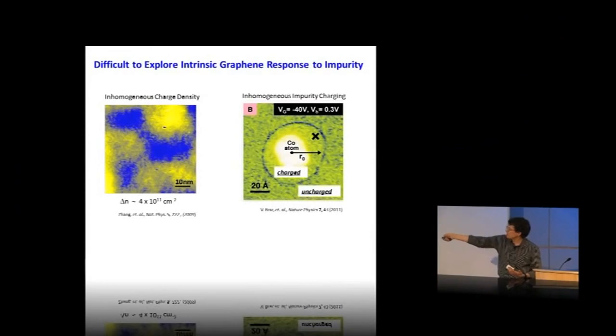Nothing is ever perfect, and one of the problems that we have, because we've been trying to do this, is that the graphene is so inhomogeneous. This is an STM image of the electron-hole puddles in graphene that you've already heard about. And this electronic inhomogeneity in graphene makes these kinds of measurements hard for us because it obscures what's happening. Because if I put one atom down, say I put an atom right there, then if there's some charge distribution around that atom due to the Coulomb impurity, it gets obscured by all of this charge inhomogeneity.